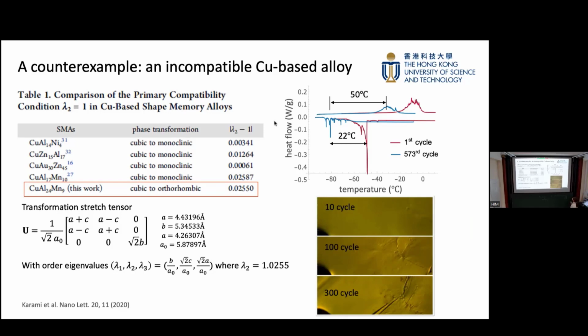We also show that if we put this material through thermal cycling, it has a huge thermal hysteresis, 50. And when we cycle it just 100 times, this material degrades a lot. We can even look at the microstructure here near the grain boundary. Initially, the grain boundary is not so clear, and after some cycles, we can see crack growth, and the material fractured if we keep cycling it, and the grain boundary goes to pieces.